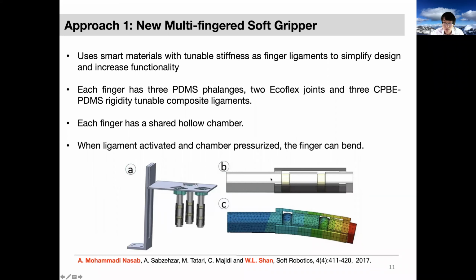Judging from the color, you can see there are 3 different components. The whitish part is the PDMS, which is relatively rigid. And for the joints, we have Ecoflex. We have 2 Ecoflex joints, which can inflate if you change the pressure of this shared hollow chamber here, which I cannot show, but just assume there's a chamber all across these multiple components.